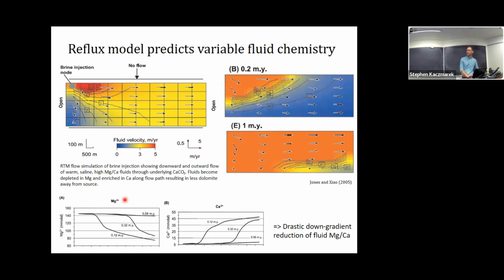One of the outcomes of this model is that with distance from where the brines enter into the limestone, because of that reaction—you're sequestering magnesium from the fluids into the mineral and liberating some calcium back into the fluid from the calcite—the magnesium and calcium concentrations change in the fluid. So down gradient, what's expected is that as we're dolomitizing, we're losing magnesium and picking up calcium.